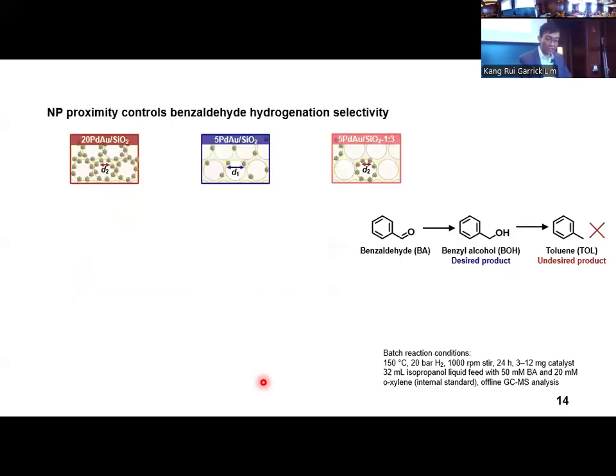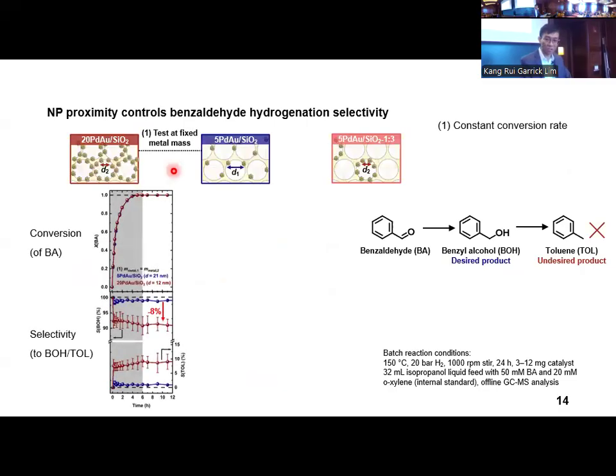We first investigated the nanoparticle proximity effect using a constant metal mass by adjusting the catalyst mass to consider the metal loading. The benzaldehyde conversion rates, as shown in the curves here, were similar regardless of interparticle distance. Interestingly, the selectivity towards benzyl alcohol was dependent on interparticle distances, as catalysts with a shorter interparticle distance show a lower selectivity to benzyl alcohol than catalysts with larger interparticle distances.